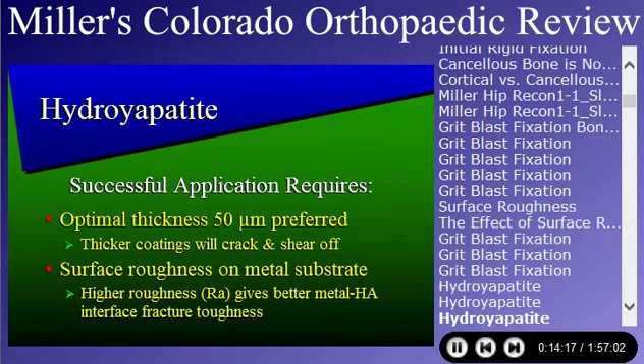The optimum thickness is 50 microns. Add that to your rule of 50s. If it's too thick, the coatings will crack and shear off. So you want them around 50 microns. Again, surface roughness of the metal helps hold this surface on. So you definitely want to put them on a grit blasted surface area, or my preference would be porous coating.